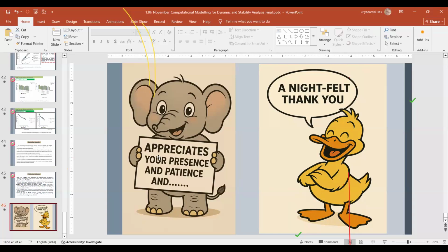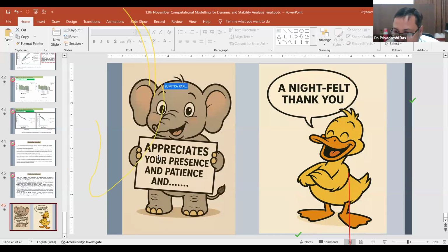So actually, in the practical case, it is not exactly true. So how are the experimental values validated in the numerical modeling, even though you have taken the same E value in all 3 directions? No. Actually, I told that it is a quasi-isotropic material. Quasi-isotropic materials mean the materials are bidirectional. Whatever material I have taken, glass fiber or carbon fiber, those are bidirectional. So if you cut the material in either the 0-degree direction or the 90-degree direction and go for tensile testing, the 0-degree direction will give the same result as the 90-degree direction. That means it is also experimentally verified that for a quasi-isotropic material you will get isotropic results, but the material is composite.